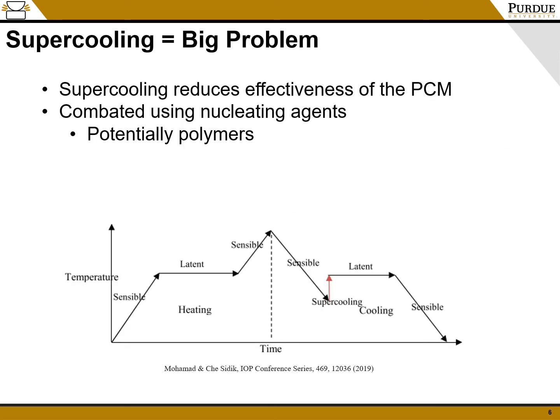Supercooling is when a material cools below its phase change temperature without going through the phase transition. This is a typical thermal cycle of a PCM where it heats up, goes through the phase change, and heats up some more, and when it begins to cool down, instead of going through the phase transition at this specific temperature, it continues to cool further until it finally does go through the phase change. It jumps up in temperature, experiences the transition, and cools down again. This reduces the effectiveness of the PCM because it's not going through the phase transition at the desired temperature.